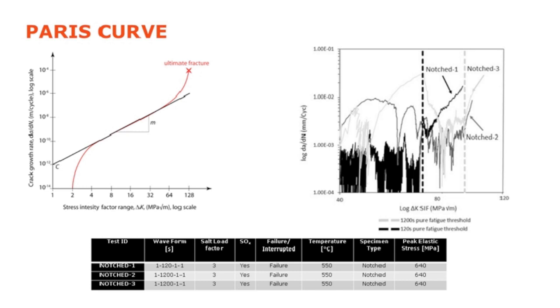On the y-axis, we've got the crack growth rate, so dA over dN, where dA is the change in crack length and dN is the change in cycles. What we see for typical fatigue, if we look at the red line, is initiation, a rapid increase in the relationship between stress intensity factor and crack growth rate, and then that levels off, so we get this flat line on the log-log plot, which represents a Paris curve, and we've got a constant and an exponent to model that. So that's our typical fatigue area, and we'll use those constants quite frequently to model fatigue.